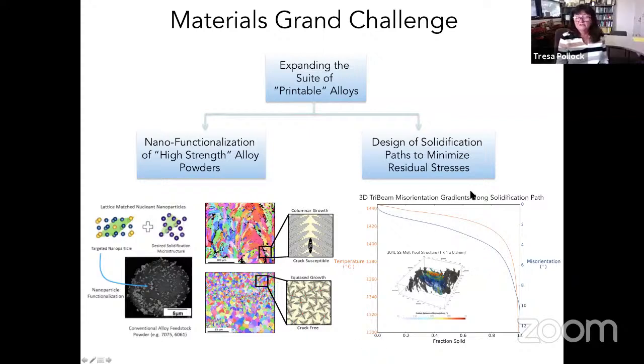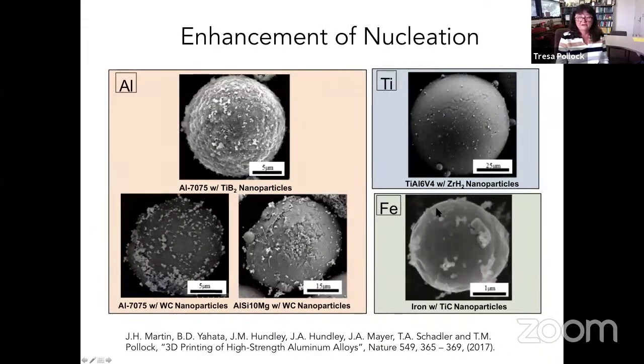On the other side of the house, where you, for example, do not want very fine grained structures, for example, in high temperature applications, then it becomes necessary to really modify the solidification path by changing alloy composition. And so here's a close-up of the functionalized nanoparticles. If you'd like to read more about this, there's a paper. But in doing this functionalization, one is able to modify the nucleation events as this powder is melted.